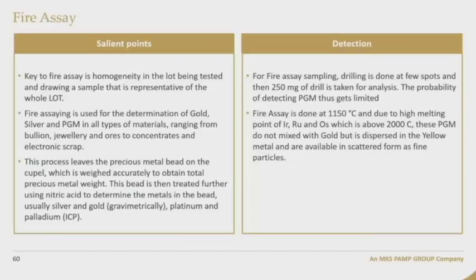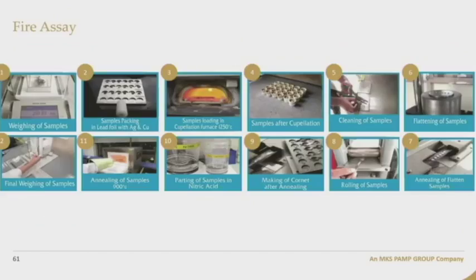And as Ankur explained in properties, the melting points of these three PGMs are much higher than gold and silver. When you are using only 1150 to 1200 degrees centigrade for fire assay, these three adulterants do not get alloyed or melted with gold and silver and remain floating throughout the melted gold, which gives a problem for the detection of those elements.